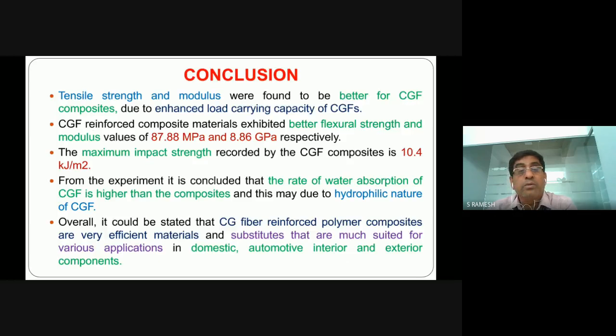And conclusion: the tensile strength and modulus were found to be better for Calotropis gigantea fiber composites due to the enhanced load carrying capacity of the fiber. Second, the Calotropis gigantea fiber reinforced composite material exhibited better flexural strength and modulus, with values of 87.88 megapascal and 8.86 gigapascal respectively. I have already told this elaborately in the graph. The maximum impact strength recorded by the composite is 10.4 kilojoule per meter square.